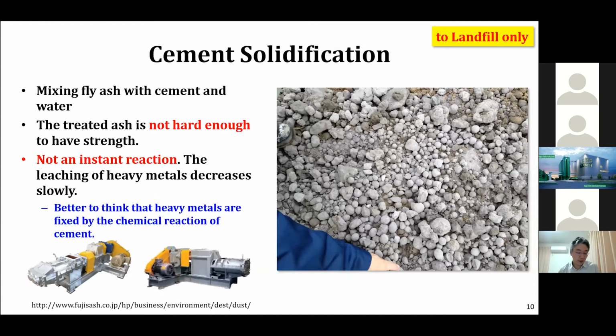The second treatment technology for landfill is cement solidification. As is well known, the process is to mix fly ash with cement and water and age it for days. Note that the treated ash is not necessarily hard enough to have a certain strength. The cement reaction is not an instant reaction, so the leaching of heavy metals decreases slowly. So it is better to think that heavy metals are stabilized by chemical action with cement.